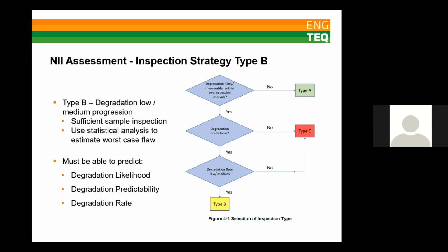Coverage in a type B inspection is typically higher than a type A. It's usually 25% as a starting point, although it may vary significantly from vessel to vessel. It may be less, it may be more. And coverage is determined using the equations that have been added to the current version of HOIS RP 103. So this is a sampling inspection, so that in the areas that haven't been inspected, it's important to estimate the worst case flaw in the areas which haven't been inspected using statistical analysis.